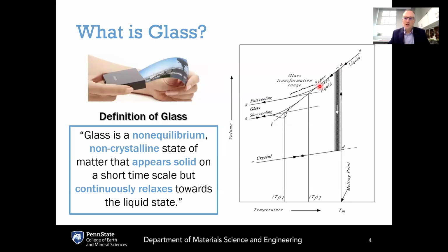And this occurs because we are observing the system on a time scale that is shorter compared to the time scale that is required for the atoms to flow. This kinetic transition is a gradual process, and this is called the glass transformation, or more commonly, the glass transition. The glass transition is this gradual freezing in process by which the supercooled liquid slowly gets frozen into the glassy state because the kinetics of the viscous flow process become much too long to observe.